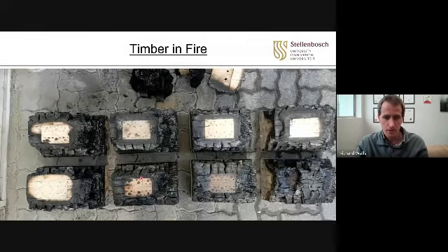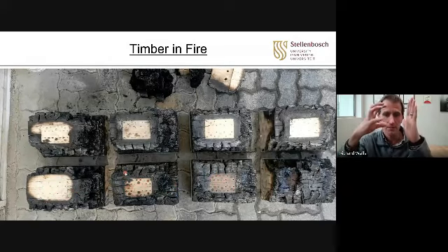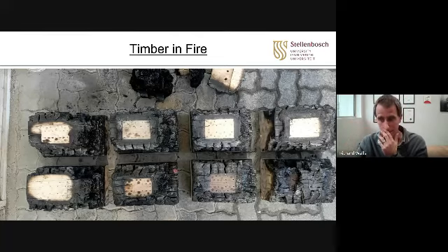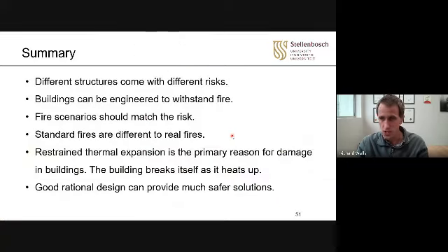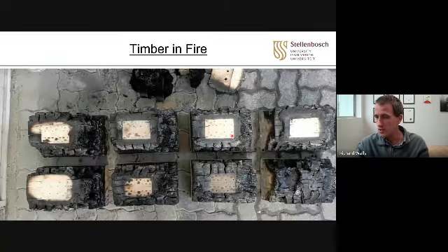That had about a 3 mm gap, 6 mm gap, 10 mm gap. So as the gap between the beam and the column got bigger, the fire penetrated further and further until that is a failure. That would have caused main structural collapse. That not necessarily. So you've got to be very careful with your design to make sure this is sufficient. So that kind of gives an overview of your main structural system.